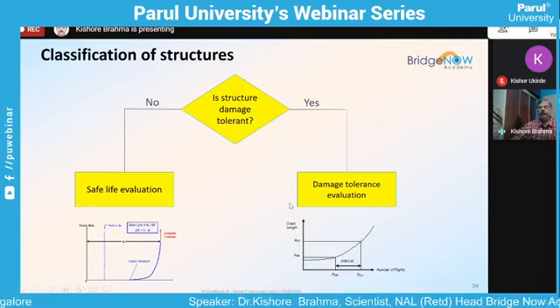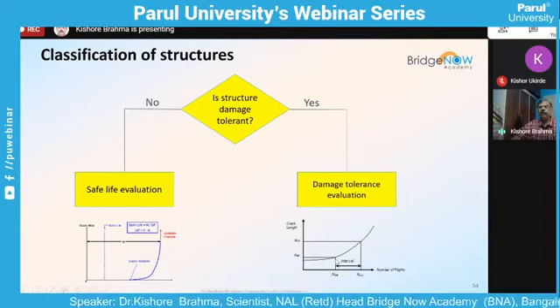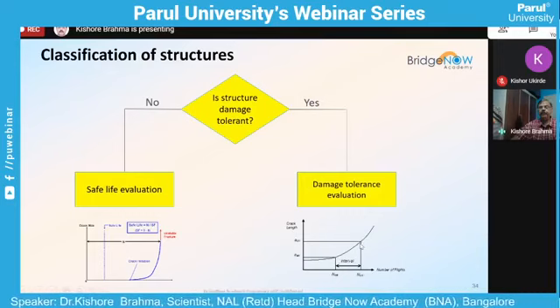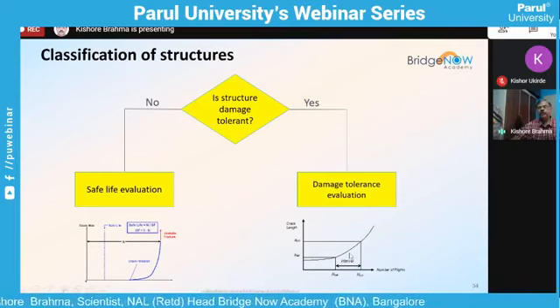But in damage tolerance, you have to do the crack propagation analysis, generate a curve, and find out at what crack length it can be detected using what type of technique you are using, and at what crack length it fails under the given spectrum loading. Then within this interval, you insert equal repeat inspections.